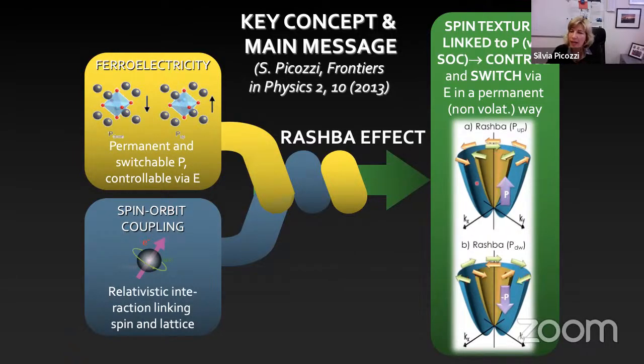So here I'm showing again the Rashba bands in the presence of, let's say, upspin polarization. And in the presence of an electric field, I will have a certain spin texture. So the spin texture here means the expectation value of the spin, of the Pauli matrices. And so for every n and k, for every state, I can calculate this spin texture. And what happens in the Rashba physics is such that, for example, my inner band has a spin circulating clockwise, and in the outer band, you see spin circulating counterclockwise.